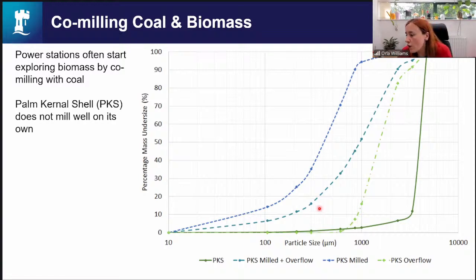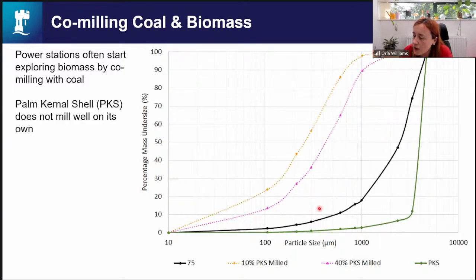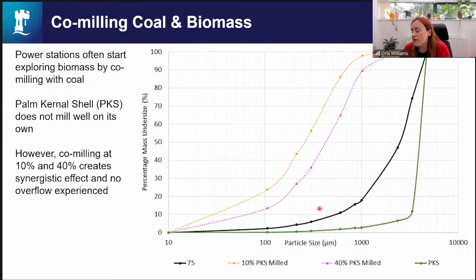Now, palm kernel shell doesn't mill well on its own. Every time it would just choke up the mill. However, we did co-milling tests at 10 and 40%, and we found there was a synergistic effect: if you milled the palm kernel with the coal, the palm kernel didn't choke anymore. You always got complete milling. So combining different materials with different properties, one being brittle, one being ductile, can actually improve the overall milling. Now, the particle size distribution you get out is coarser than what you would get with just the coal, so that obviously has a knock-on for combustion. But there are benefits to co-milling different types of materials together to overcome some of these choking issues.